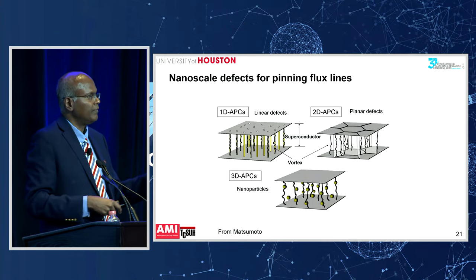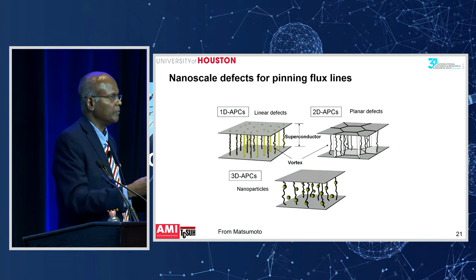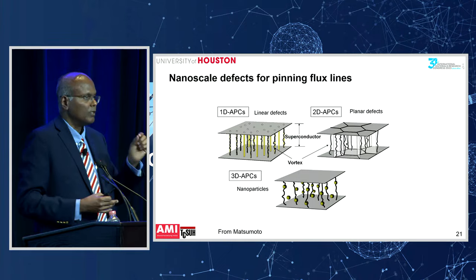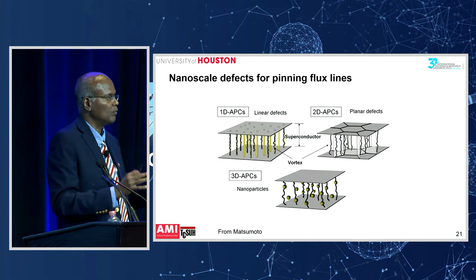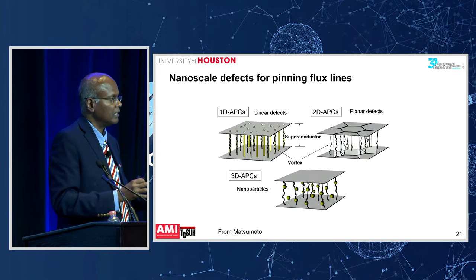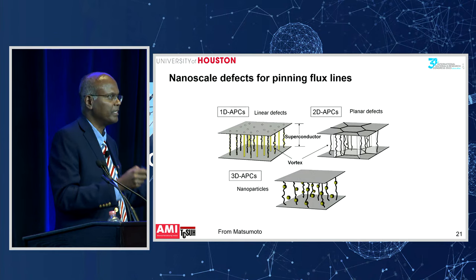And if you can do that, then you can actually go to much higher currents before the vortices break loose and move around and dissipate energy. So ideally, you want to have the defects at the same scale as the vortices. These vortices are typically a few nanometers in size, which means the defects should preferably also be in the range of a few nanometers. But how do you implement that in an epitaxial film? That is a challenge, and many researchers worked on this, and I'll show the results from our group.